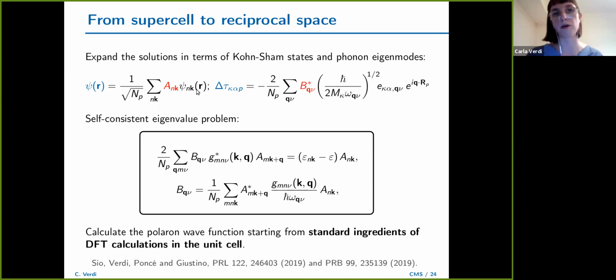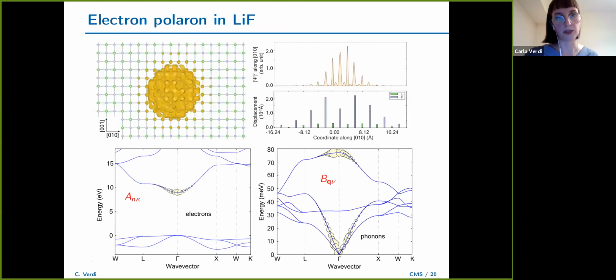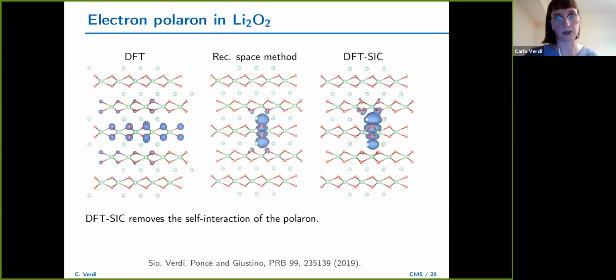You could argue, okay, how do you know that this is a good enough approximation? Well, this is why we validated the theory a posteriori. We validated this both on the small polaron in the case of lithium fluoride, but we also validated it using the standard Fröhlich polaron model for the large polaron case. So if you're doing a hole polaron, then it's a sum only over the occupied states.